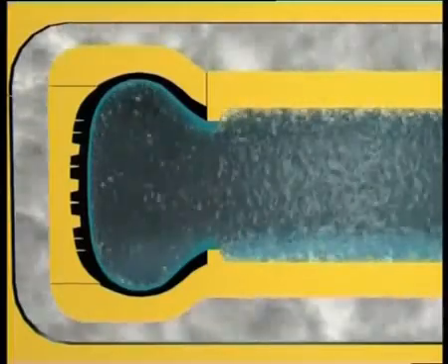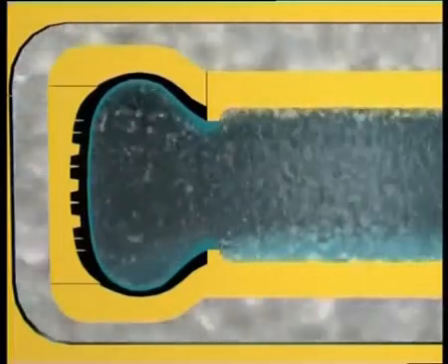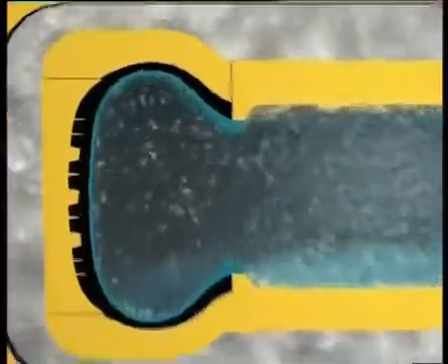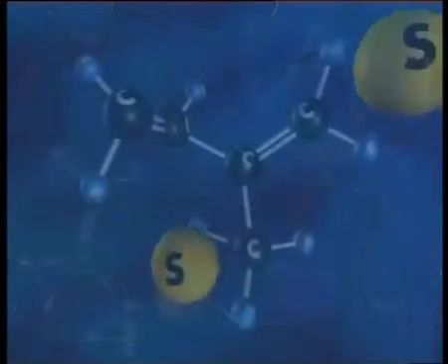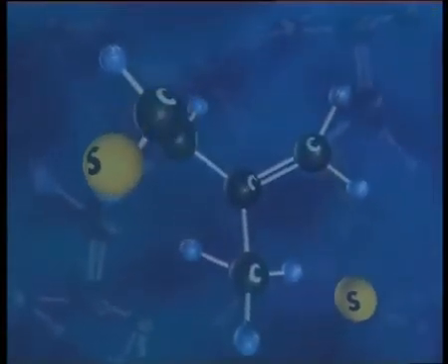The heat of the water and steam surrounding the mould will cause curing to begin. The rise in temperature causes vulcanisation of the rubber. The sulphur incorporated into the rubber compounds forms bonds between the polymer chains. At this point, the rubber switches from a plastic state to an elastic state.